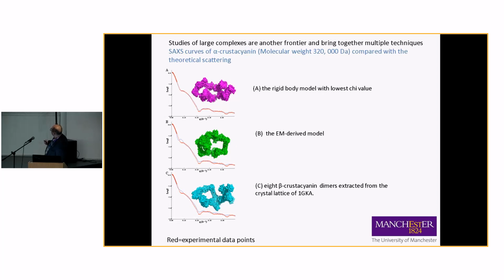And what we can do by looking at our crystal lattice, and we can see similarities, and we can try and fit the solution X-ray scattering curve with these different models. These are called lower resolution techniques, and they give you a feeling for overall shape. And EM in particular, by using liquid nitrogen, liquid ethane temperatures, is now actually reaching atomic resolution for things that you can't crystallize. How far it will go is a matter of open debate in the field. Things like distinguishing metal atoms with the X-ray wavelength tuning is believed to be out of reach of cryo-electron microscopy.